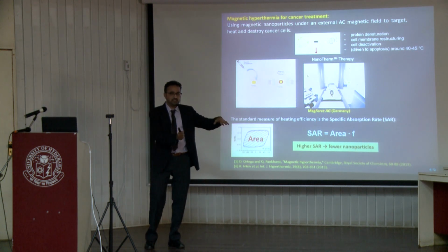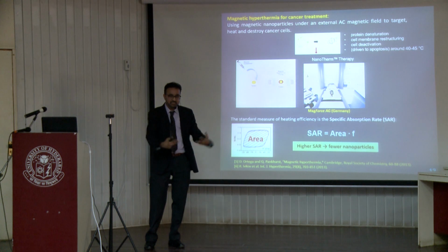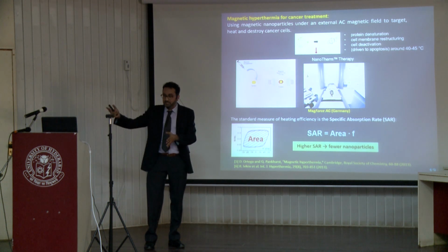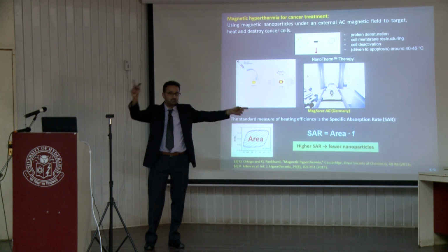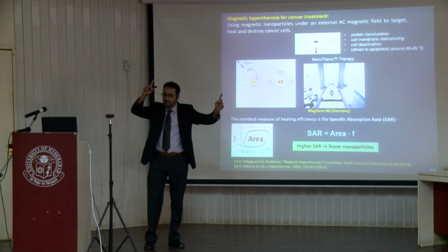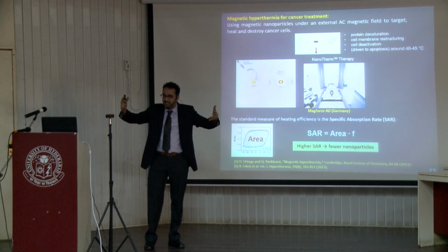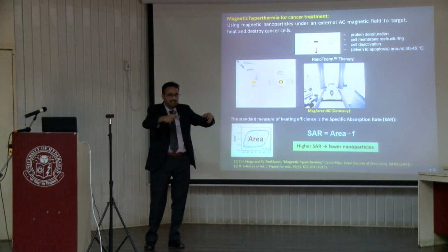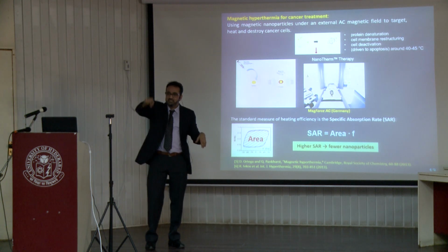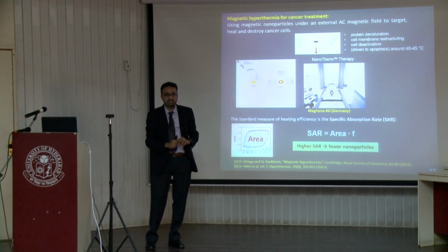As you reduce the temperature, below a certain temperature, the internal energy, namely the anisotropy energy, exceeds kBT, the thermal energy. So these fluctuating moments freeze randomly. As a consequence, you get something that looks like a spin glass. And in magnetization measurements, you can see that as a drop in the susceptibility. So that's the signature of that.